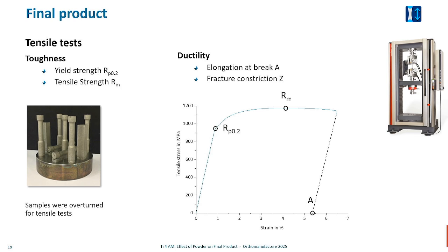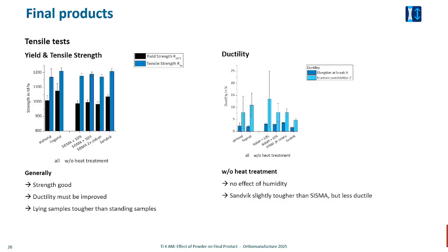So we did tensile tests, as I said, with samples which were printed in laying direction or in upright standing direction. We determined the classical parameters like yield strength, tensile strength, or elongation at break. The strengths show some difference between standing and laying. So laying had some higher tensile strength, and ductility was slightly higher, but highly scattered overall. So there's a tendency that laying was better in this case than standing.